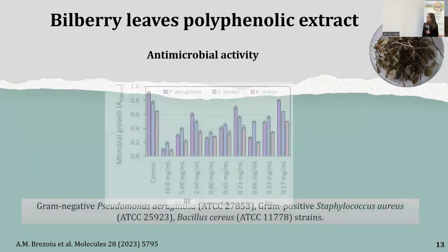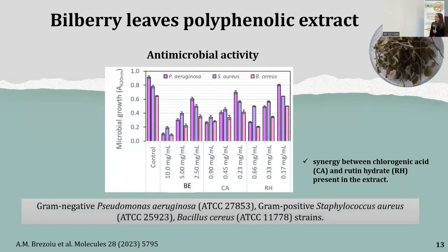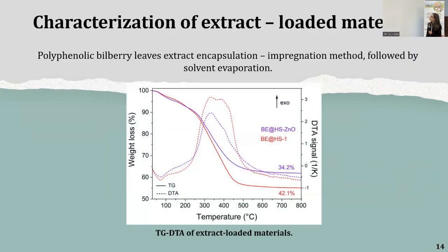An interesting aspect is the synergy between chlorogenic acid and rutin hydrate present in the extract. The microbial growth inhibition is significantly higher than the one of separate standard compounds found in the extract. The content of encapsulated extract was evaluated by thermal analysis, shown in this image.